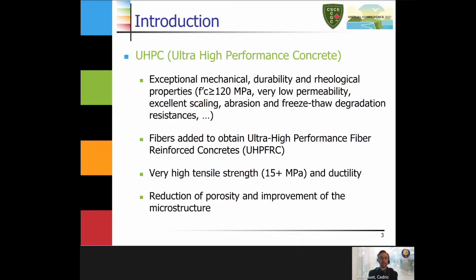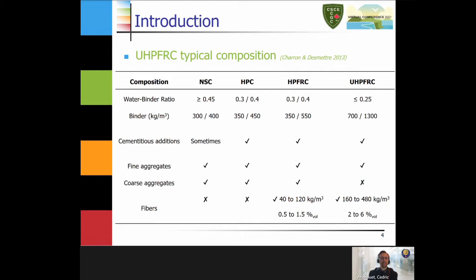Ultra-high performance concrete are materials that present exceptional mechanical, durability and rheological properties. Typically, we have a compressive strength higher than 120 MPa, a very low permeability, excellent resistance to scaling, abrasion, freeze-thaw degradation, etc. When we add some fibers to those materials, we obtain ultra-high performance fiber reinforced concrete. And those have very high tensile strength, up to 15 MPa, sometimes more, and a very interesting ductility as well. And typically, those are obtained by reducing the porosity of the material and improving its microstructure. This leads us to the typical composition of a UHPFRC.